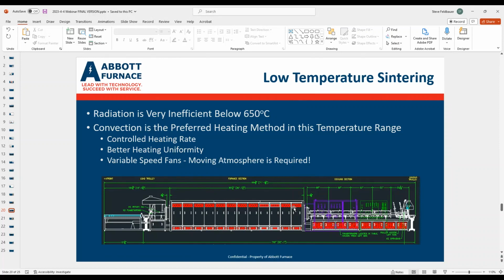to debind and sinter these lower temperature materials that have a much smaller window between where they melt and where they sinter. So this type of system is a different design for the lower sintering temperature materials.